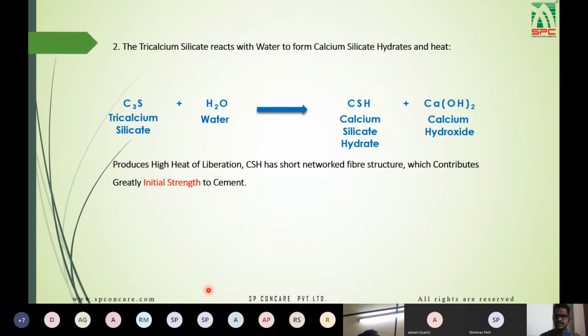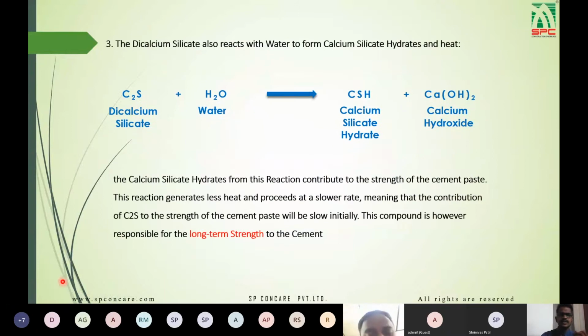The CSH produced, that is calcium silicate hydrates, has a short network fiber structure, which contributes greatly to the initial strength of the cement. The next reaction is the reaction of dicalcium silicate with water. The dicalcium silicate also reacts with water to form calcium silicate hydrate and calcium hydroxide. Similar to the previous reaction, but the difference is this reaction is much slower and produces less heat. The calcium silicate hydrate from this reaction contributes to the strength of the cement paste.